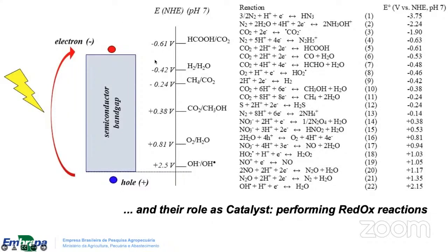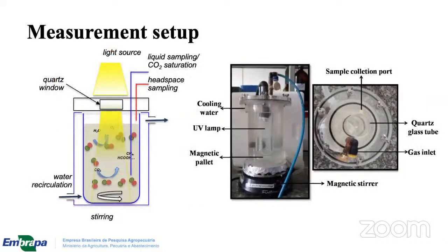In terms of the relative position of these reactions, most of the semiconductors have adequate positions, but the problem is how to increase this interaction with the CO2. And what we can do is try to select the semiconductors using freestanding particles instead of electrodes. These freestanding particles have more interaction with CO2, and in most of these cases, we can analyze the products by analyzing, for instance, the liquid along the time, or analyzing the headspace after some time of the reaction.